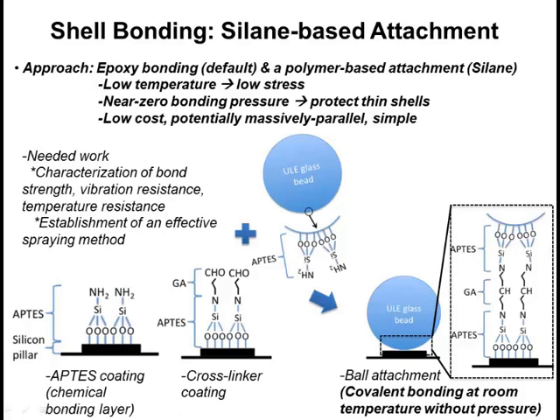To form this support, we need to have a bonding method, and we have a couple of bonding methods developed in our university. One of them, by Professor Hanseup, basically uses APTES, which is a derivative of silane, to stick the coated molds onto a post. And the second one is using a glass frit.